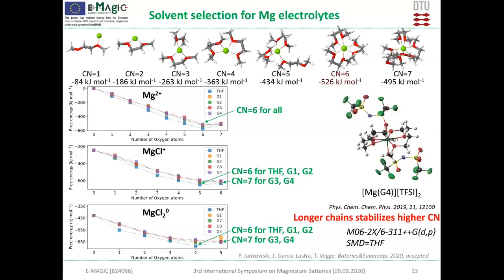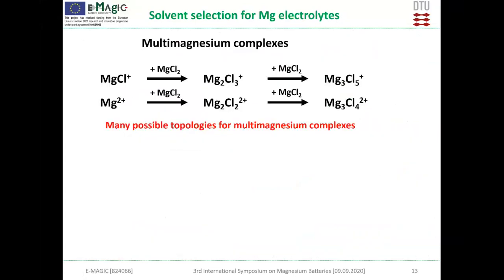So then we wanted to go also to more advanced systems, so with multimagnesium. And these multimagnesium clusters can be seen as a result of the reaction of the simple clusters together with MgCl2 with a salt, creating the dimers, so clusters with 2 magnesium or even 3. We could go also further, but DFT calculation is getting very, very expensive if we include much more magnesium. So we have to stop here. But what we can say is that even here we have a lot of topologies, how the atoms are arranged, and we need to test all of the examples to know which one is really the one that's providing the lowest energy.